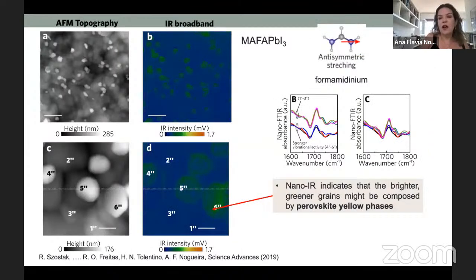We did many experiments at the time, but I'm just focusing on the yellow phase. So this is the point spectrum. As you can see, this is at high magnification, the AFM topography, and the infrared broadband image on the right. Let's take image D, okay? What we see is a different color. It means that these grains are different from the grains underneath. And then you can just set your AFM tip there and get an infrared spectrum.